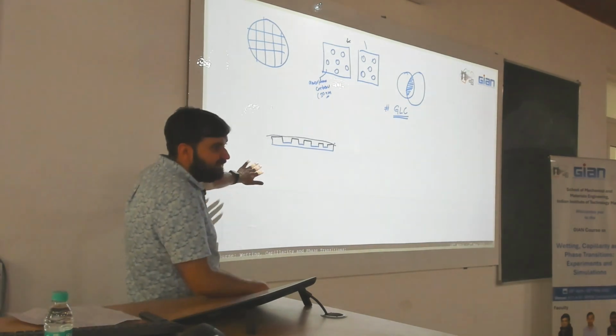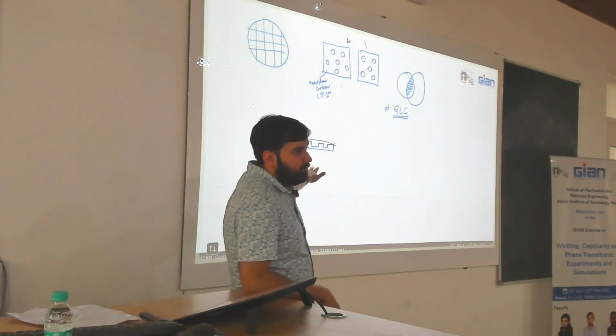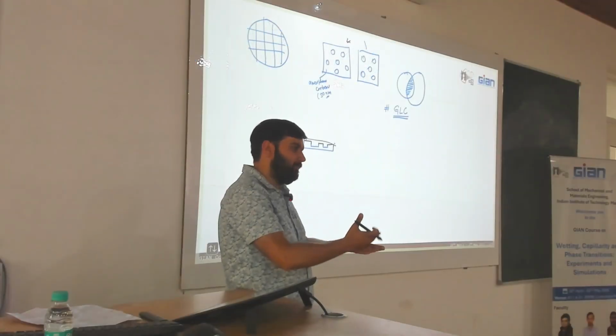But remember that these bubbles are just gas bubbles. They are not vapor bubbles. We have tried to fill the complete cell with liquid, and then we have tried to heat it, and we have tried to put the electron beam in such a low configuration that radiolysis doesn't occur, so that all the bubbles which are formed are vapor bubbles. But that hasn't happened. What happens is that complete drying of the sample occurs. So we are able to see the interface, but never a bubble.